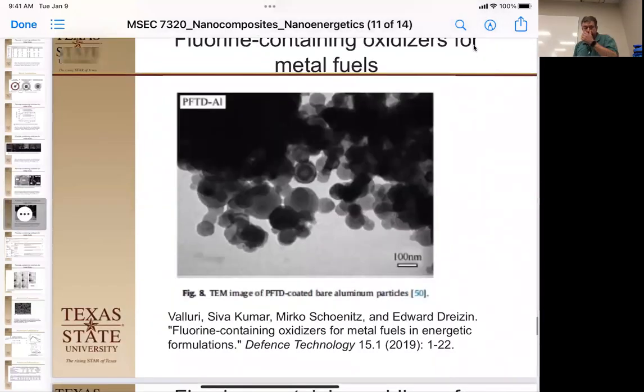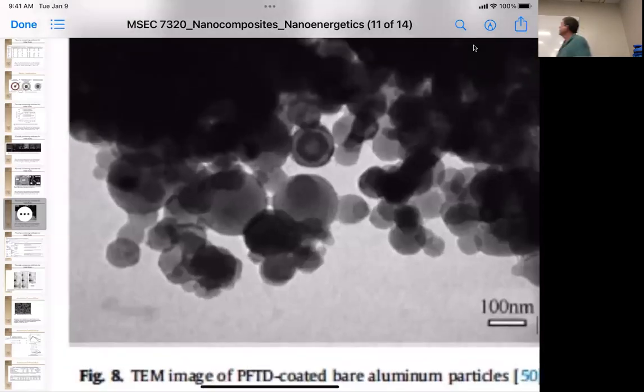And when we look at the TEM of this, some of them have a little grid pattern in here. You can actually see the crystalline aluminum on the inside. It'll have that crystal packing pattern on them. But it's showing that they are fairly well dispersed. I think the dark ones might be aluminum and the lighter ones might be Teflon, just because of density. But usually you can see the little fringes in the aluminum powder. Oh, these are Teflon coated bare aluminum.